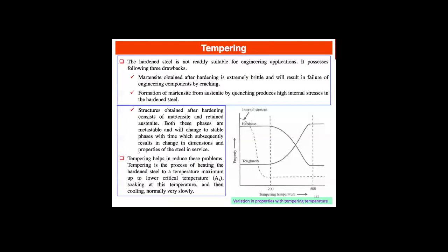So depending on the service condition, they can change, right? It's okay if you're going to keep your steel in the Arctic. But if you're in the tropics, depending on what your in-service conditions are, these phases can revert to the stable ferrite and cementite. And so tempering is not just about getting a little ductility back. It's also making sure that you're at a stable structure.